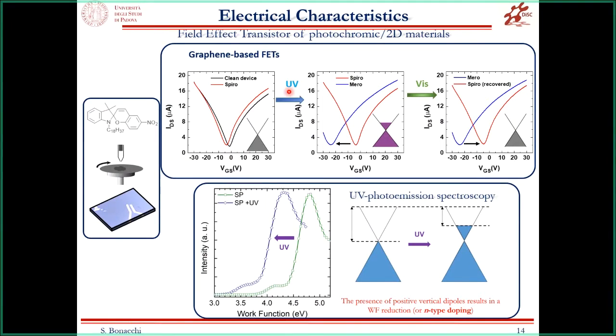But as soon as we shed UV light on this film, again the dry film, we observe a very strong n-doping effect, so a very strong shift of the Dirac point of graphene to negative voltage, and we were also able to go back upon visible light. So we were actually able to prove, thanks to this field effect transistor measurement, the possibility to play with high-order assembled molecules, and to play with light to switch the electrical properties of a 2D material.